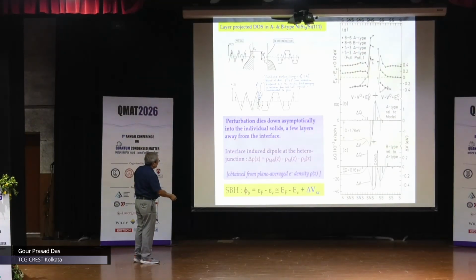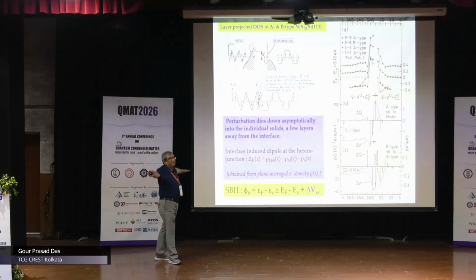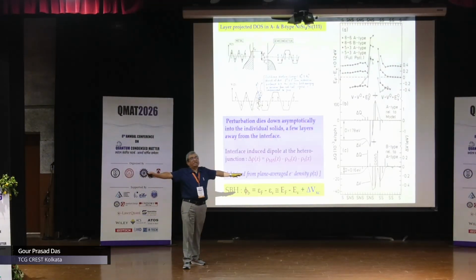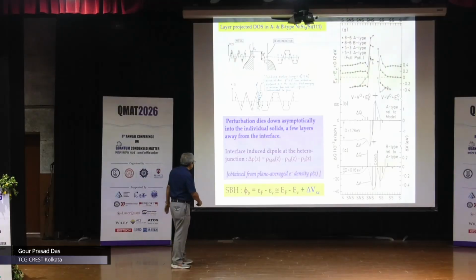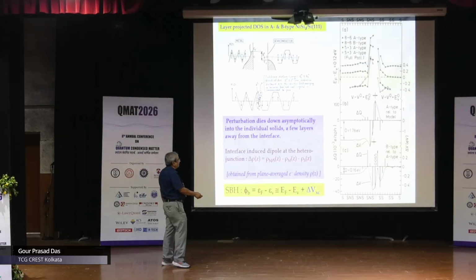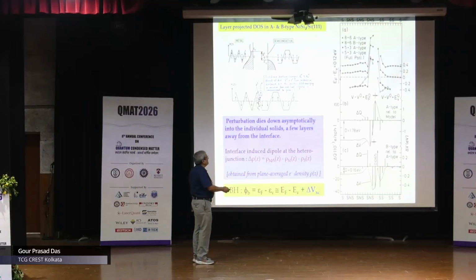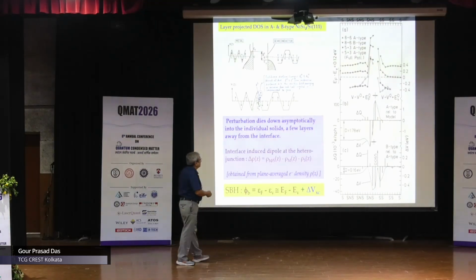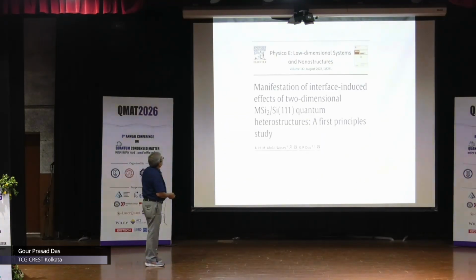barrier height. So basically, it is the density functional based Fermi level minus the density functional based valence band top, plus the delta VXC, which is the change in the exchange correlation functional when you go to plus infinity and minus infinity. Okay, so this is something which we estimated with great accuracy, and we did find out the difference between the A type and the B type Schottky barrier height, the difference of 0.15 electron volt we could find out.